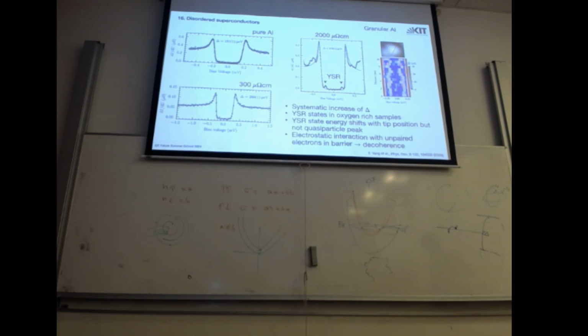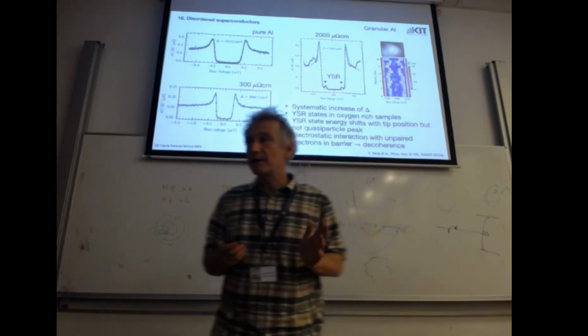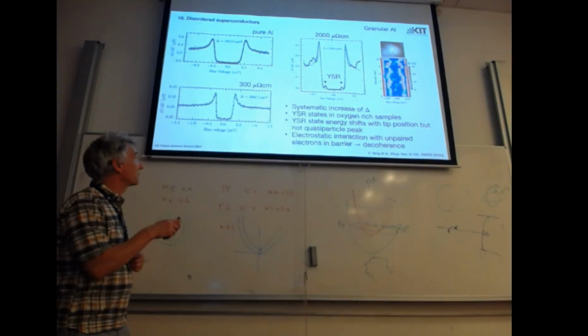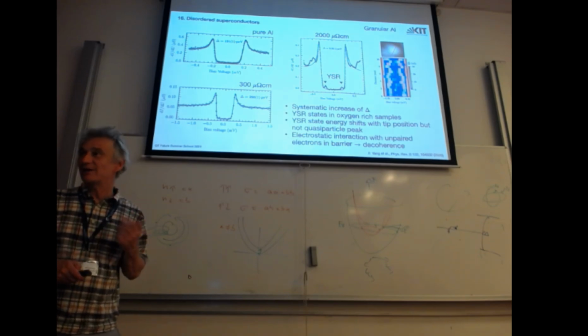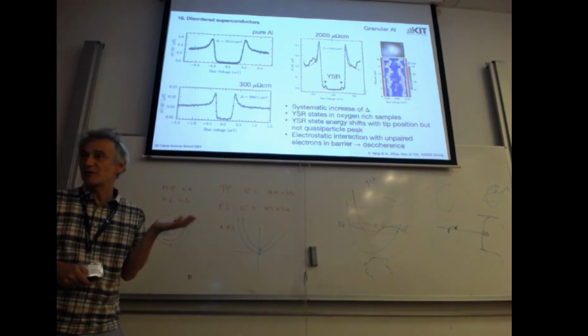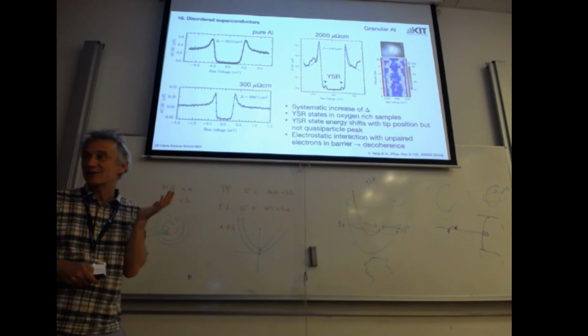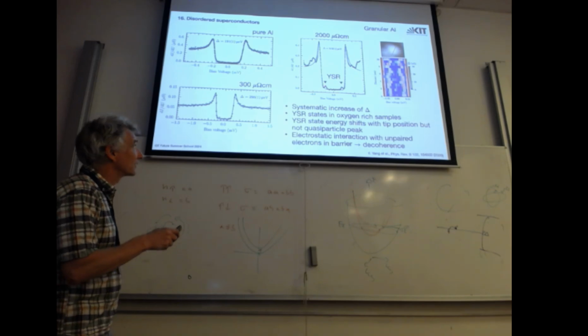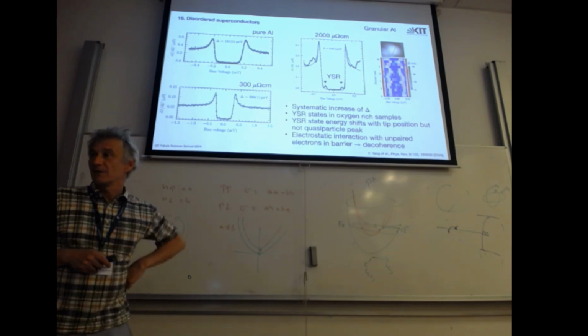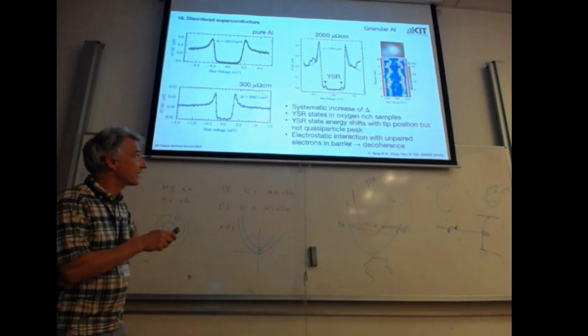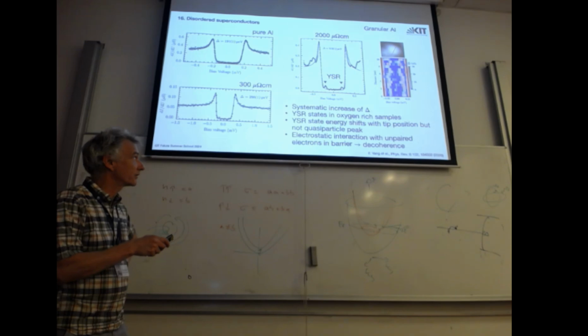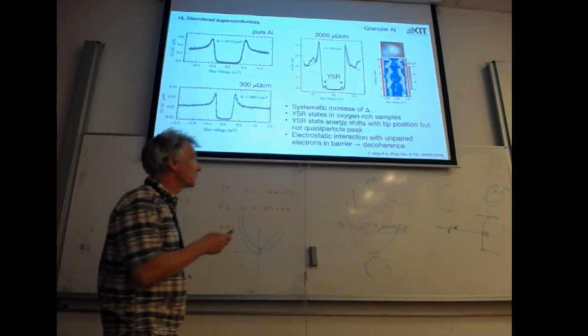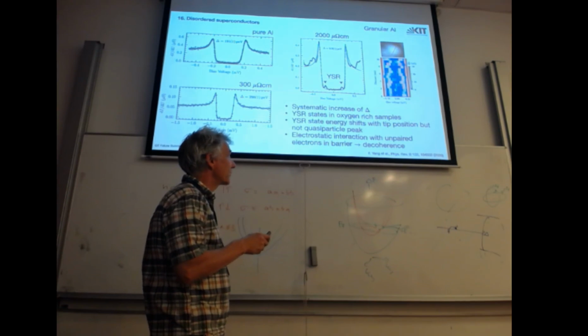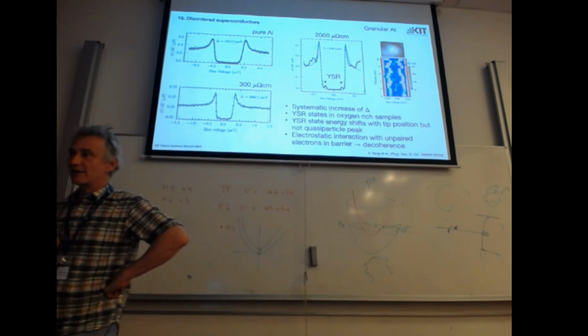And if I move over my grain, I see this gap is hard, it does not move in energy. So with my local gating of the tip, the electric field at the tip, it does not shift in thermal energy. So I will not change the number of electrons. But the YSR state shifts. So I have no electric field here inside the grain, but the YSR state will shift. And this can only mean that these localized spins are in the oxide, where the electric field can penetrate.